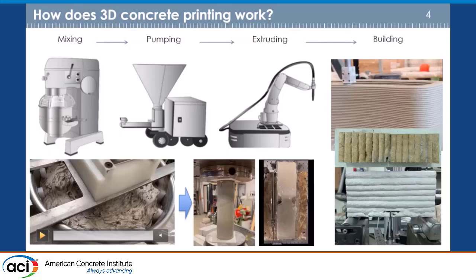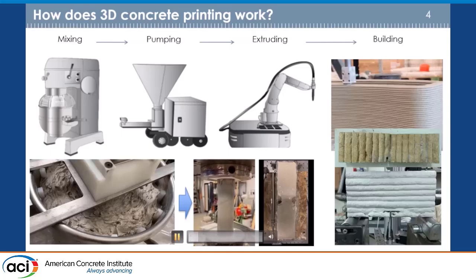So if you want to make a rheological test with rheometers, you need extremely powerful rheometers. This is a picture from an ICAR rheometer we have in our lab. You need to cast liters and liters of concrete, and most of all this does not comply with the 3D printing equipment facilities. It has been quite a challenge also to test the material performance at very early ages. This is a compressive strength test done at 1 hour on a specimen, and it's something that we need. And for tensile tests, well, also some methodologies have been developed, borrowing them from self-compacting concrete technology.